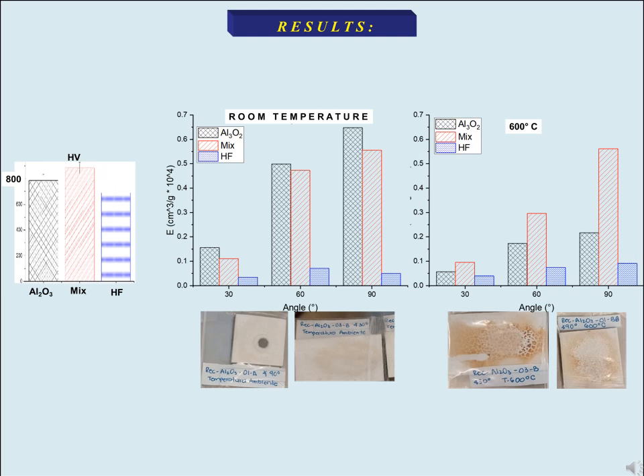For the high-temperature erosion values, 600 Celsius degrees, there was a brittle behavior for the ceramics, as in the previous case, but for the alumina coatings, there was an apparent decrease in the mass lost. It was explained due to the adhesion of silica from the erodent particles, and this happened only at high temperatures, as can be seen in the image below the graphs. Again, the hard-facing materials, the blue bars, showed the best results.